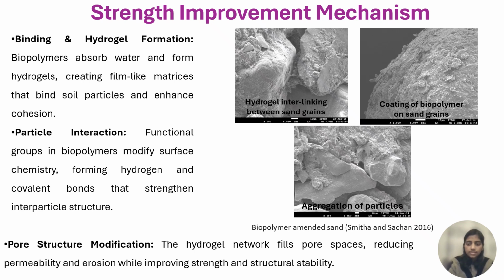The second mechanism is particle interaction. At a smaller scale, the biopolymer molecules have active groups, things like hydroxyl and carboxyl groups, so they can bond with the mineral surfaces. They form hydrogen or covalent bonds which strengthen the contact between the soil particles. This effect is especially strong in clays and silt, because the clay particles are smaller, so the surface area available for bonding is larger.